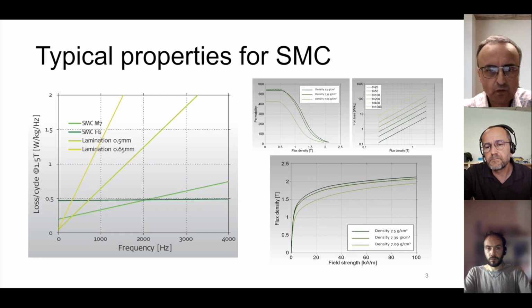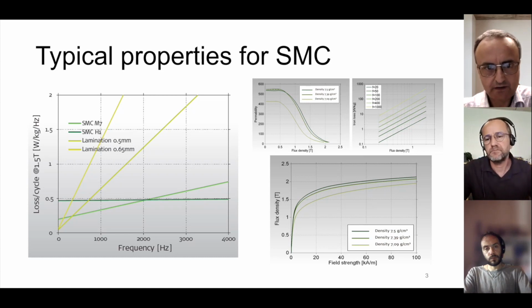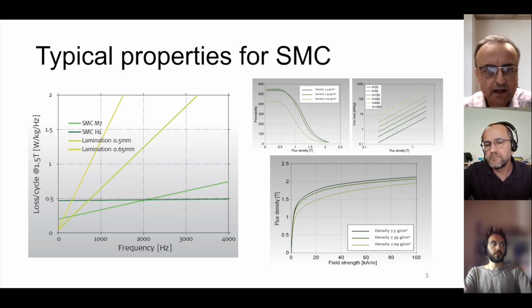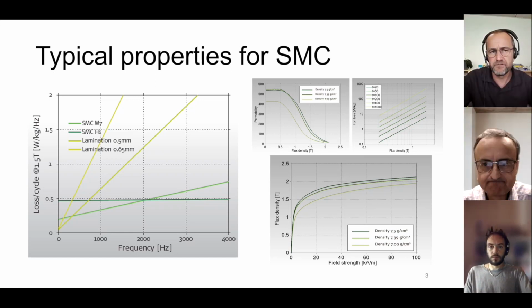Typically, for higher frequency, you would go for thinner laminations. So here you have the losses for 0.5 and 0.65, but those thickness values would not be so well suited for applications going above, let's say, 1 kilohertz or so. Normally you would go for 0.35 or something like that. And in such a case, you'd have lower losses for eddy currents, because the thinner the lamination, the lower the eddy current losses for the same level of flux density. Yeah, so typical thickness is 0.35 in industrial applications today.